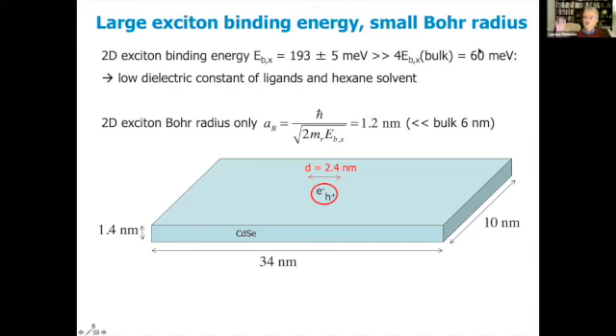And that is much higher than 4 times the bulk energy. So if you just reduce the dimension from 3D to 2D, then theoretically you expect a 4-fold enhancement of the exciton binding energy, but 4 times the bulk binding energy would be 60 millielectron volt, and we have more than 3 times higher exciton binding energy, and that we think is due to the low dielectric constant of the surrounding solvent, that's hexane, and the organic ligands. And from this exciton binding energy, using the two-dimensional hydrogen model, we can calculate the exciton Bohr radius, which then turns out to be 1.2 nanometers.